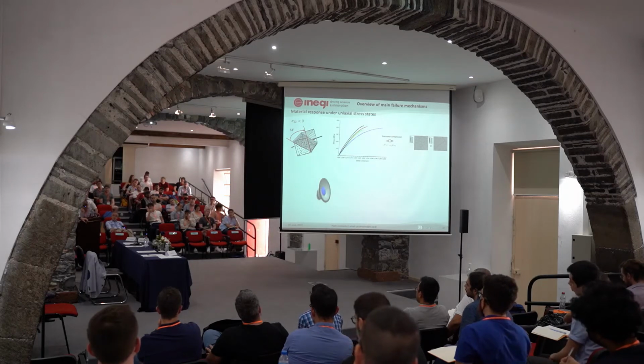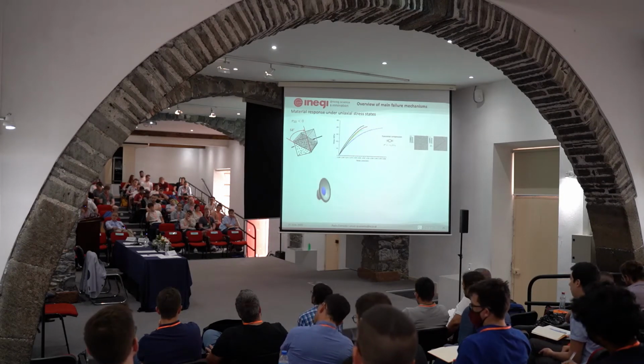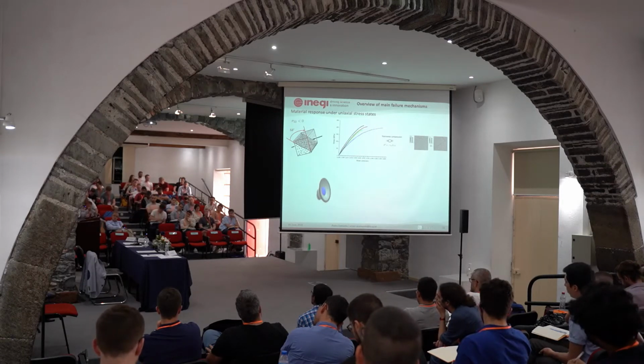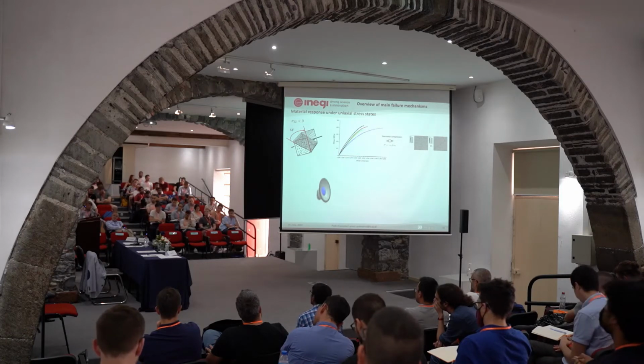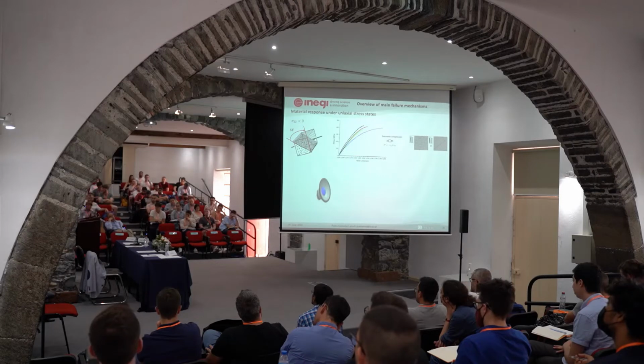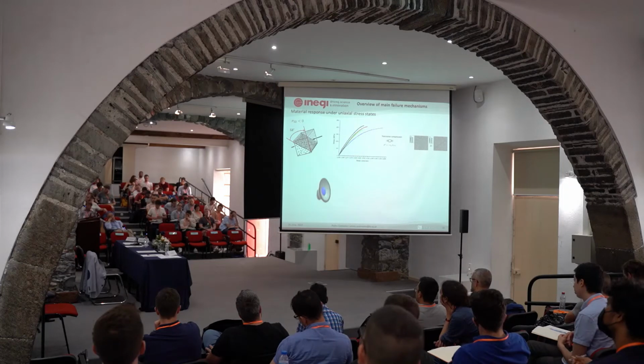Okay, in my opinion, when it comes to strain, it's more complicated because you don't have the onset of damage that starts in locations that are more prone to develop this damage. Since you don't have a periodic distribution of reinforcements, you have a weak spot in your material that needs to be captured. Okay, so damage is not controlled by mean fields; it's controlled by local fields. So with direct numerical simulation, we can of course get compressive modulus or any other property, but we do it mainly to understand that.